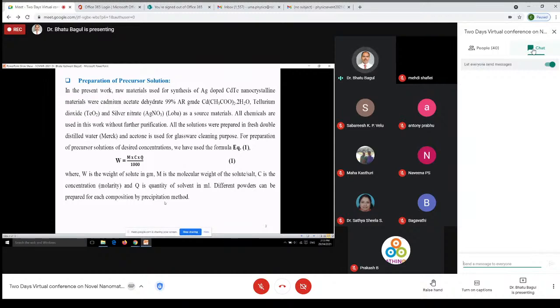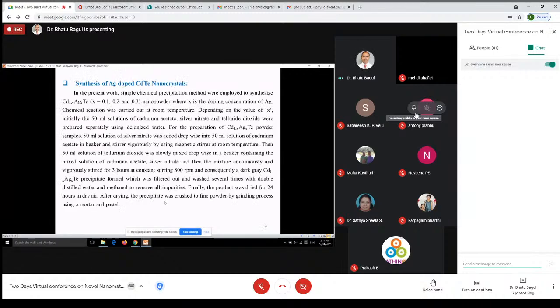For the preparation of the solution, we use the formula W = MCV divided by 1000, where W is the weight of the solute in grams, M is the molecular weight of the solute, C is the concentration, and V is the quantity of solvent in ml. In this way, we can prepare different types of powder having different concentrations.